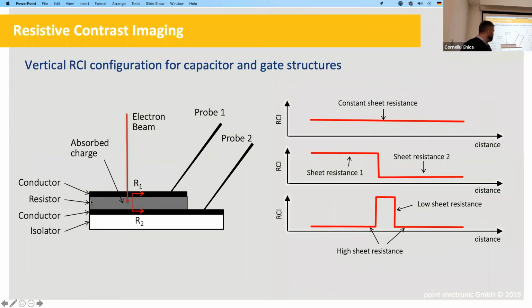Another geometry is we have an oxide to build a capacitor, most typically would be a capacitor, so a thick oxide. And it could be between two metal layers, or it could be between a metal layer and a poly, and so on. And now we have the structure vertical. It's not sideways, it's vertical. And the way we do this is that we use the electron beam again to put the absorbed current just at the right depth, so they will be in the oxide. And then again, we split the current, but not sideways, we split it top and bottom. So some of the current will come to the top, some of the current will go to the bottom.